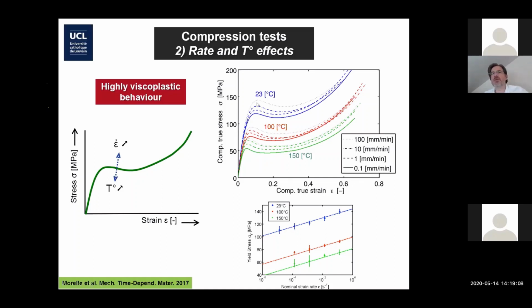So by the way, at room temperature, for the metal people in the audience, it's good to realize that the yield stress of these materials is above 100 megapascals. So compared to a typical aluminium alloy, not the best one, we're not far. So yield stress is large. Of course, the Young's modulus is close to 3 gigapascal, which is way lower. But the yield strength is really decent when compared to many metals.